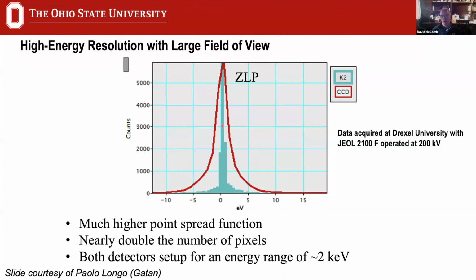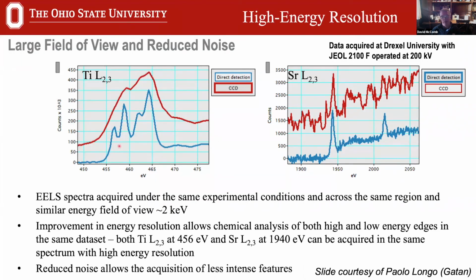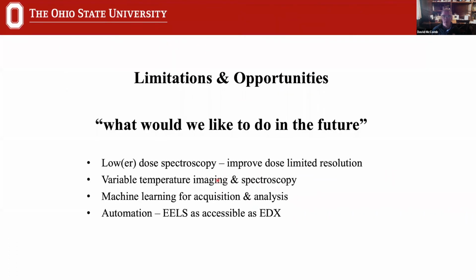These two spectra are our zero loss peaks. I get this from Paolo Longo, but it's a zero loss peak acquired under identical microscope conditions, the only difference is in green, we have a spectrum acquired on a direct electron detector, and in red, we have our conventional CCD detector. And you can see that the reduction in the point spread leads to improved energy resolution without doing anything else in terms of the electron optics. And that then opens up these same kind of comparisons, looking at titanium and strontium edges. And there's a lot of potential, particularly as we look towards higher energy edges, for exploiting this performance.